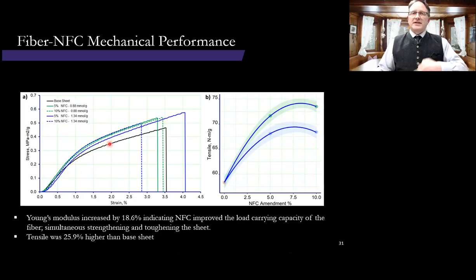Same trend at the low percentage high: toughness of the sheet improved, but then it dropped and we lost all our gains when we started seeing those electrostatic repulsion effects. And at the high charge with tensile, we still got a much better improvement for tensile than the base sheet, but not nearly as high as with the low charge.